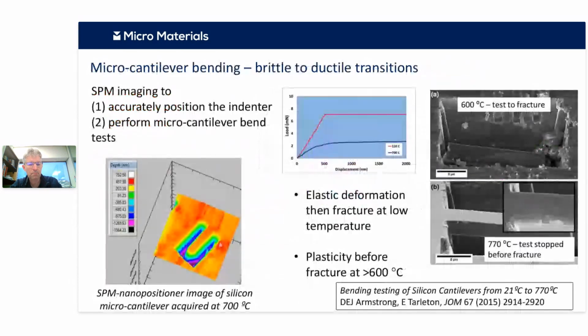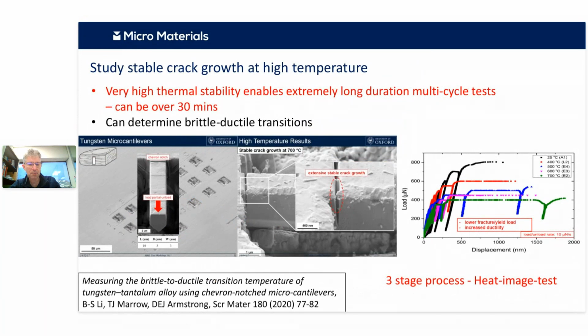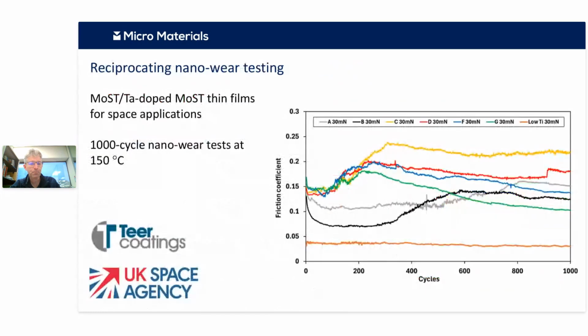Okay, so certainly James has talked a fair bit about these deformation of beams. So this is a much simpler, earlier version at the University of Oxford, where they were just looking at single bending of beams to fracture and looking at temperature dependence there. That one, as James has talked about, so I won't really say any more, apart from the fact that it's the stability of the instrumentation that allows these long duration multi-cyclic testing. And then say a methodology approach from heating up, imaging the surface, then doing the testing is a very simple workflow in the nanotest system.